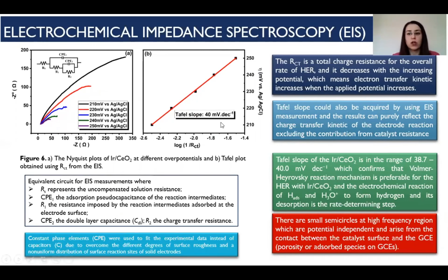Tafel slope also can be acquired by using impedance spectroscopy, and the results purely reflect the charge transfer kinetics of the electrode reaction, which excludes the contribution from catalyst resistance. The Tafel slope of the iridium ceria, 40 millivolt per decade, confirms that the Volmer-Heyrovsky reaction mechanism is preferable for the hydrogen evolution reaction with iridium ceria. There is also a small semicircle at the high frequency region, which is potential independent and arises from the contact between the catalyst surface and the glassy carbon electrode.